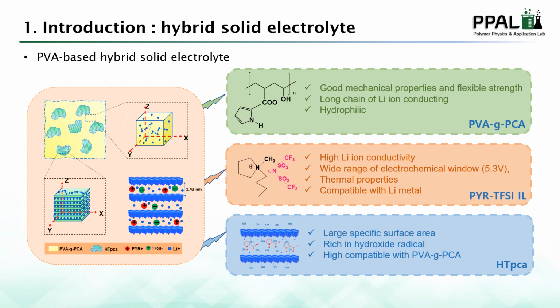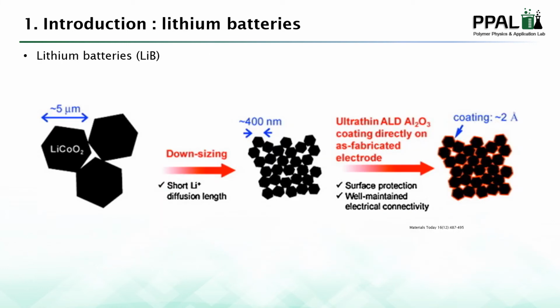On the other hand, the HTPCA nanoconductor was introduced to the PVA-grafted PCA ionic liquid-based electrolyte to further increase the lithium transfer number and reinforce the integrity of the whole battery system. As this structure mimics the sequence of functional groups of PVA-grafted PCA, the HTPCA nanofiller was quite compatible with the PVA-grafted PCA ionic liquids and thus possibly supplies additional 2D free-wave lithium transfer paths as shown. And the nanocontainer of the HTPCA creates selective transfer towards the lithium ion to enhance the lithium transfer number because of its small dimension, and also restricts the transfer of the bulky ionic liquid cluster composed of the PYR pyrrolidinium cation and TFSI anions, and suppresses the oxidation and decomposition of active material.